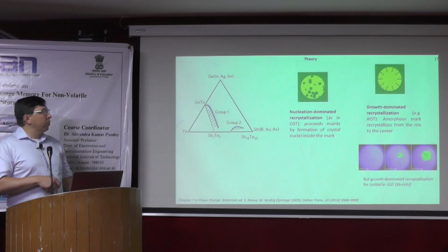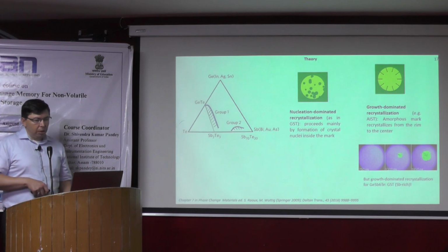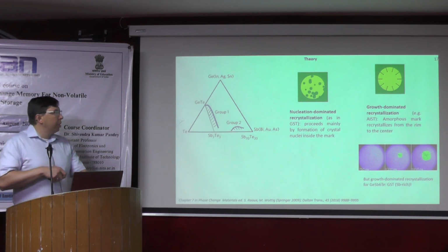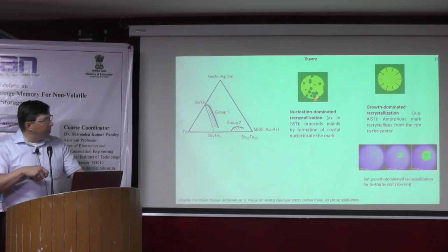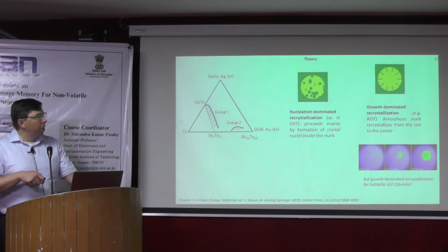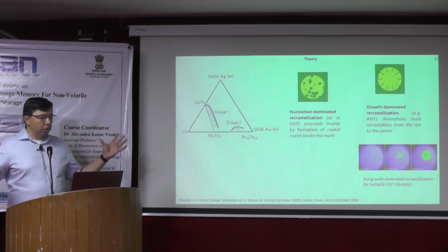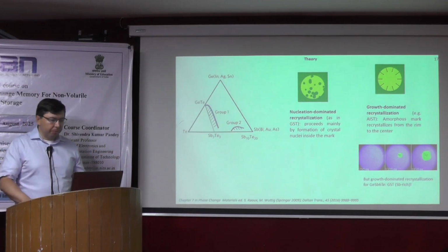So what is the difference between these two recrystallization processes? In one, the crystallization kinetics is dominated by nucleation, so you have many nuclei. They nucleate, and then they grow a little bit. In the case of growth-dominated crystallization, as soon as you have a stable nucleus, it starts to grow to a large crystal.